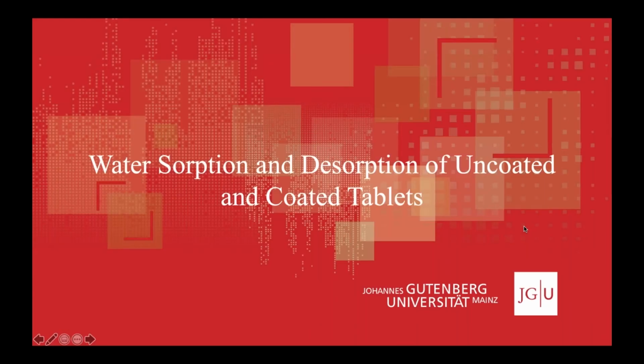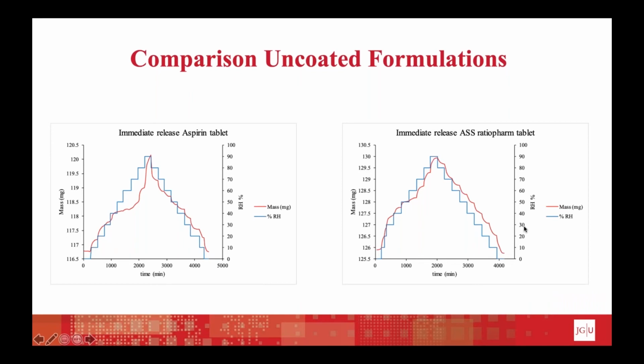The second example was the water sorption and desorption we did on uncoated and coated tablets. In our case, we used two brands that are on the German market, the Aspirin and the ASS Ratiopharm tablets. In this case, they are not coated, and what we can see is that for the Aspirin tablets, for example, an absolute mass increase of around 3.5 milligrams, and for the Ratiopharm brand, even up to 4 milligrams.